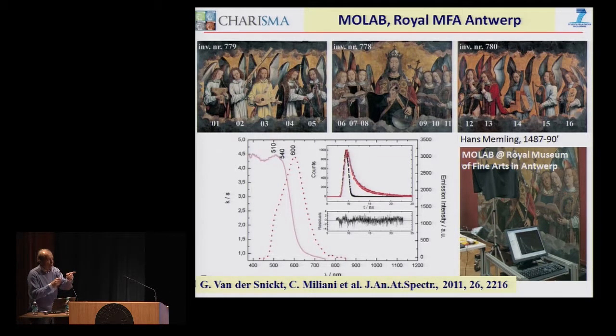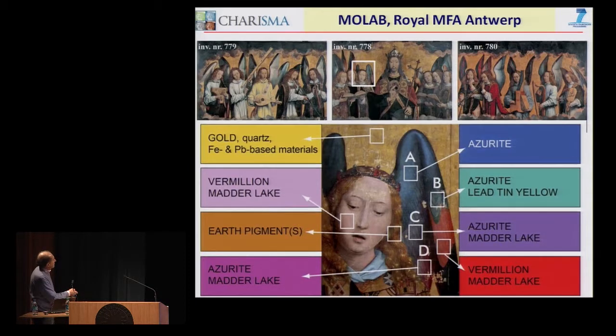the same point using a unique optical fiber that then has different ramifications. So observing a unique point, you can carry out measurements in absorption, measurements in emission, and measurements in decay time of the emission. And through these three measurements at the same time on the same point, it was possible to characterize the presence of madder lake. In this part of this triptych, here you see, this mixture was identified with azurite on this wing, here in mixture with vermilion on this part of the wing of the angel, here together with azurite again to create this cangiante effect, and here on the face of the angel together with some vermilion.